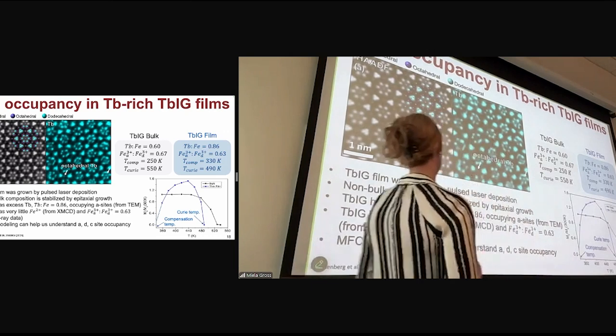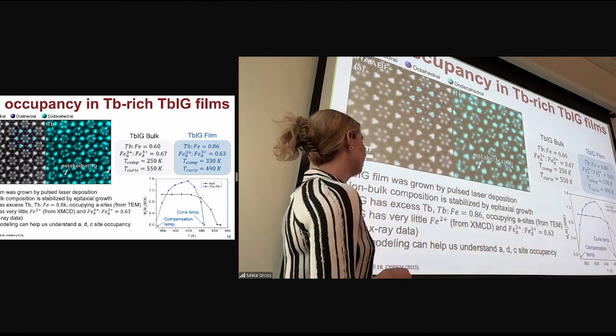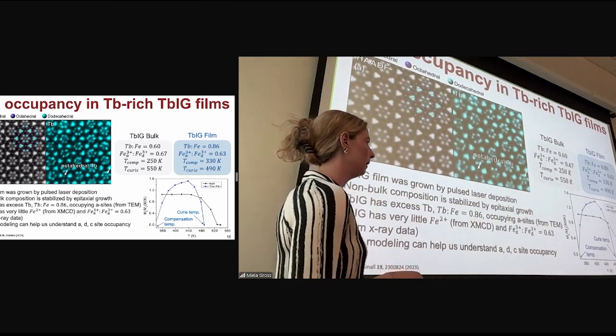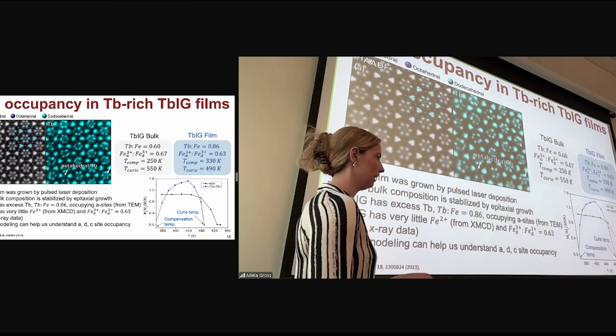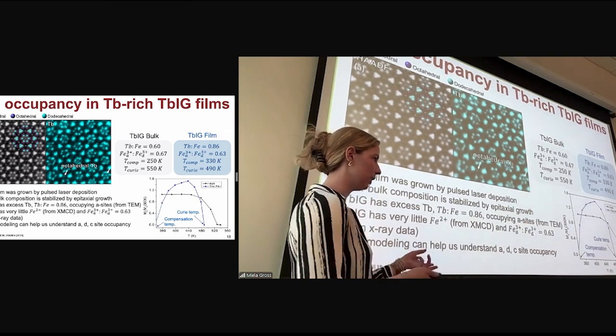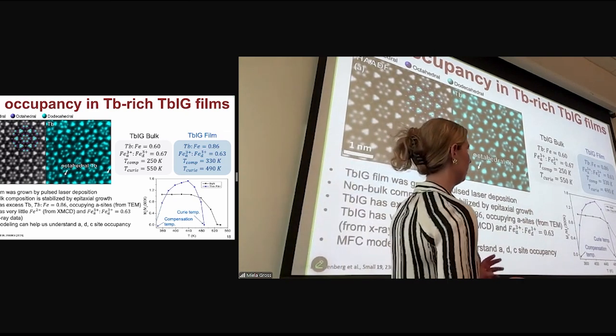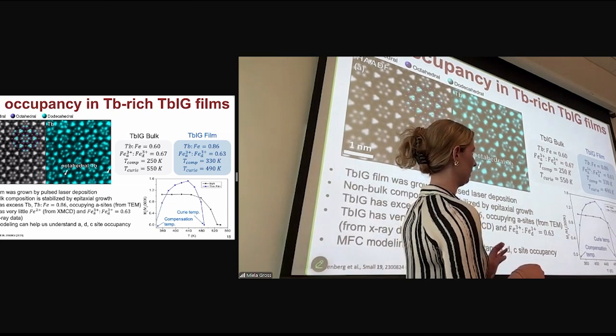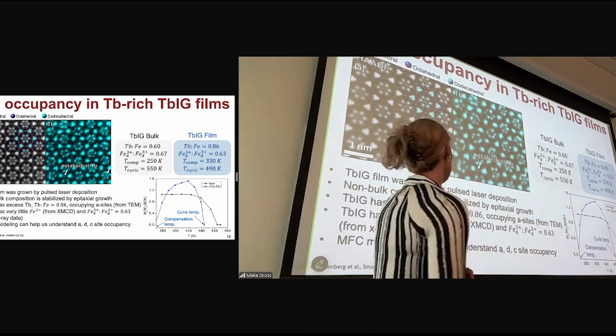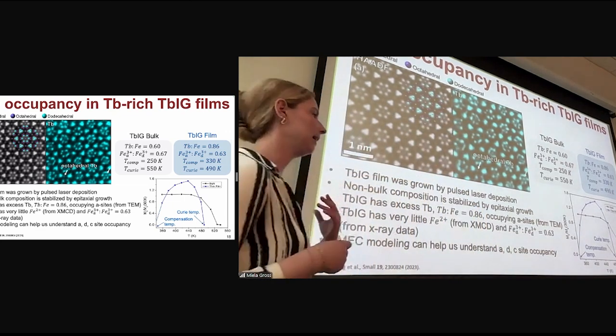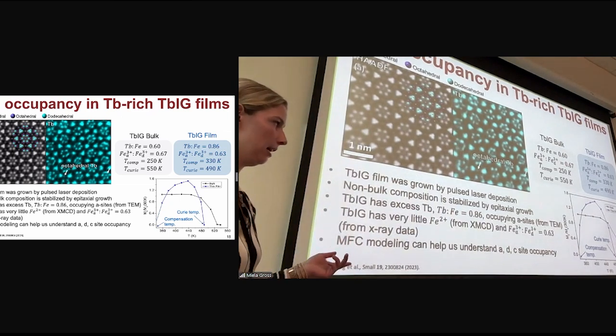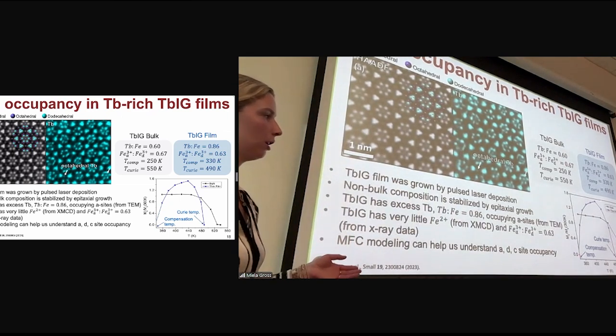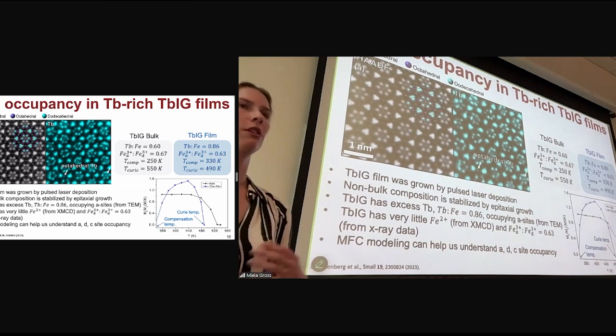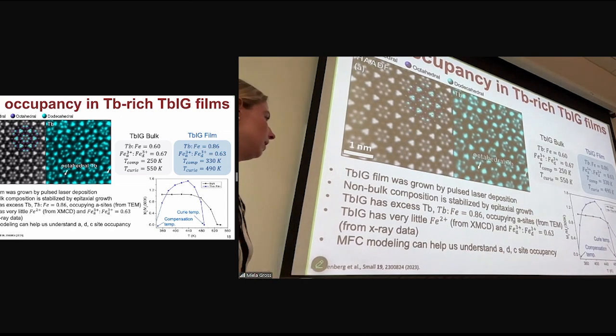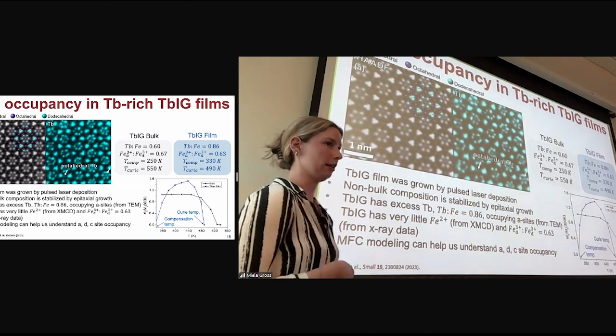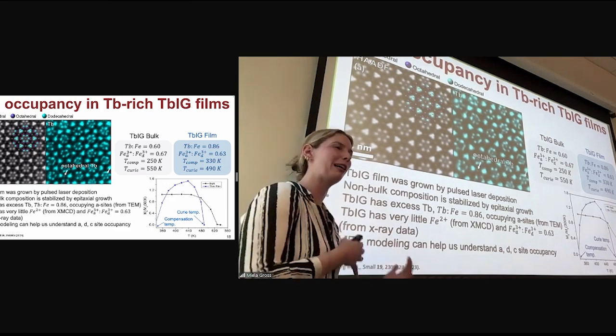He also found from XMCD data that there was very little iron 2+, but the iron octahedral to tetrahedral, or A site to D site ratio, is 0.63, which again is off from what you'd expect in a bulk composition. He experimentally took data of the MS versus temperature curves of these samples, so we could use our molecular field model to understand what the A, D, and C site occupancy were here, because we have a few more unknowns than knowns.